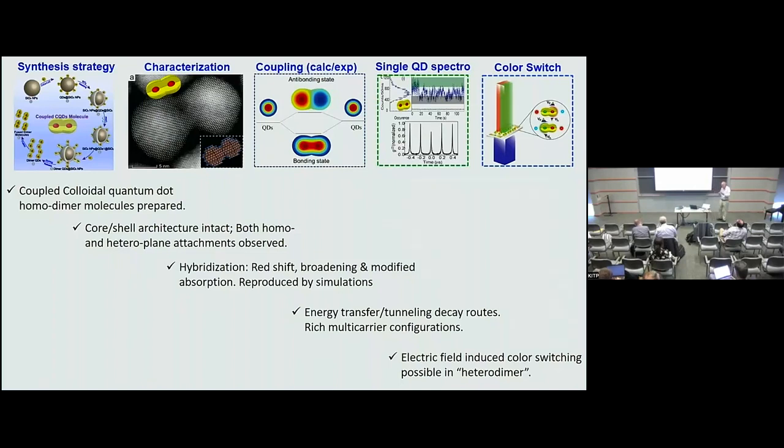What people have done, and we have these experiments also, is that under a field you can use a nanorod, you have more volume, and then you can actually get a larger Stark effect if it's oriented with the long axis along the rod. But here, the main point is that it's a switching effect rather than a shift and change of overlap. The idea is that you still maintain overlap of electron and hole on one side or the other side, so the intensity is not supposed to change too much when you switch from side to side.